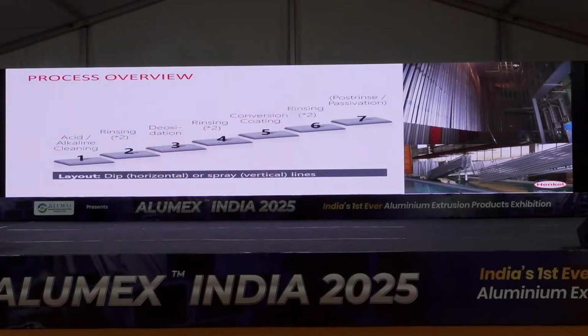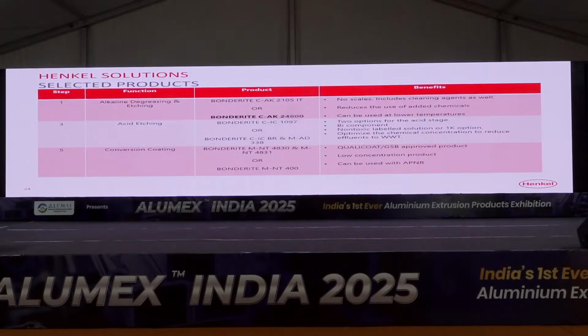We have different proposals. The first proposal is our traditional chrome-free, which has been in the market for more than 20 years, with a lot of square meters treated all over the world. We have other ones that I will explain later, but let's go for the traditional one. It can be applied in a layout of, for example, a horizontal or vertical spray line. You start with an alkaline cleaning, rinses, the deoxidation of the surface, and then it is ready for conversion coating and rinse. It is true that the rinse before the conversion needs to be of the best quality possible. If possible, DI water is much better, or otherwise a maximum of 100 microsiemens. So this is a Henkel solution.